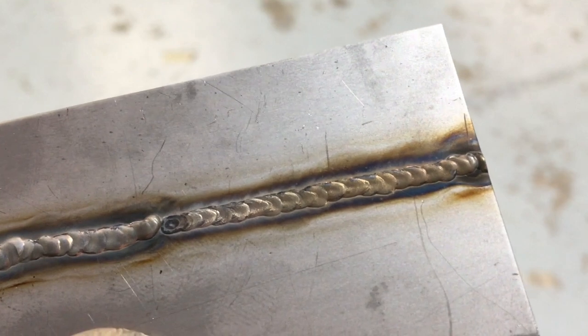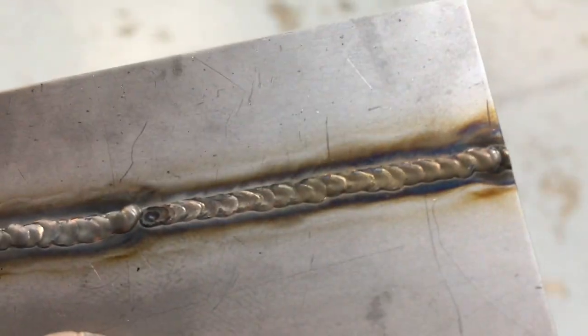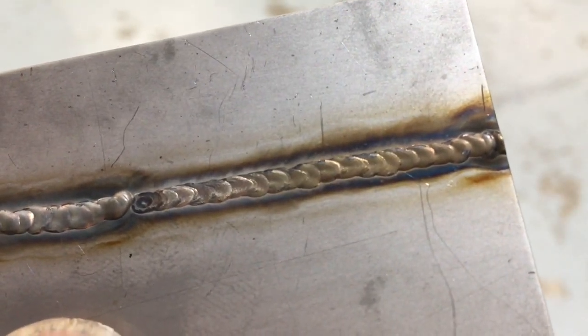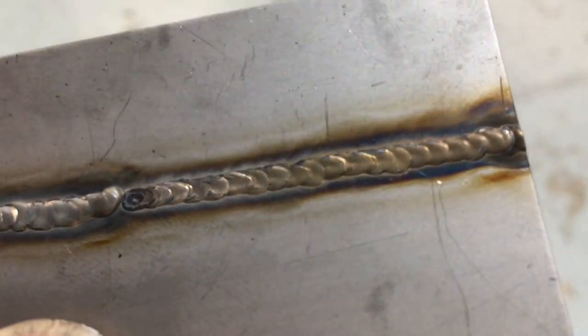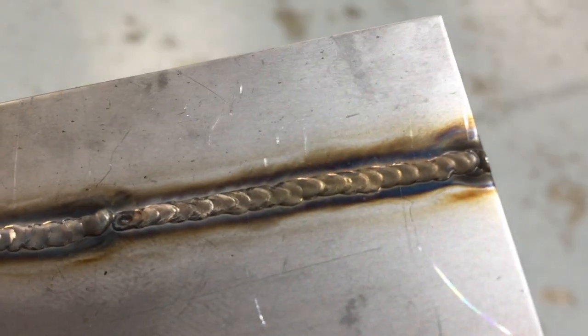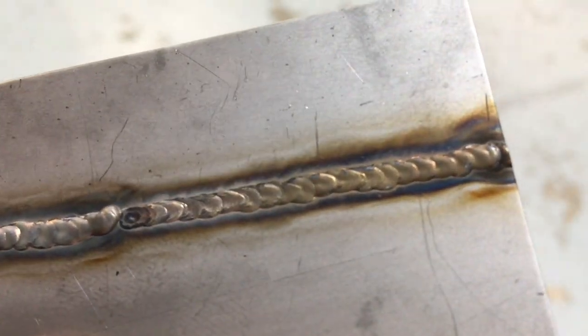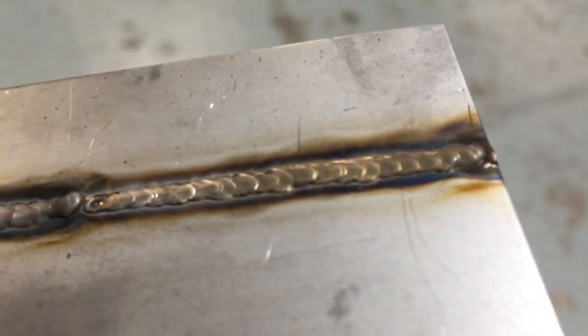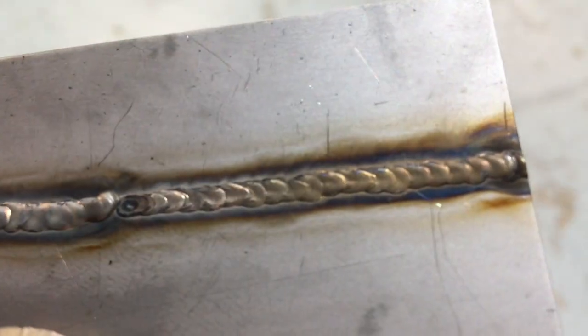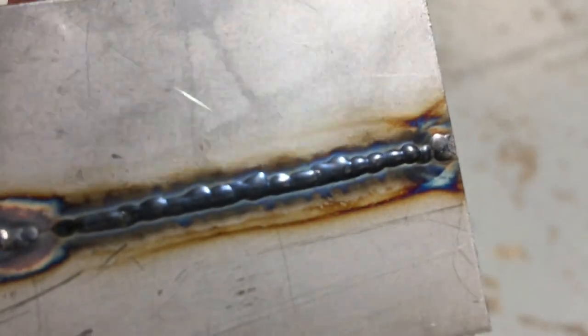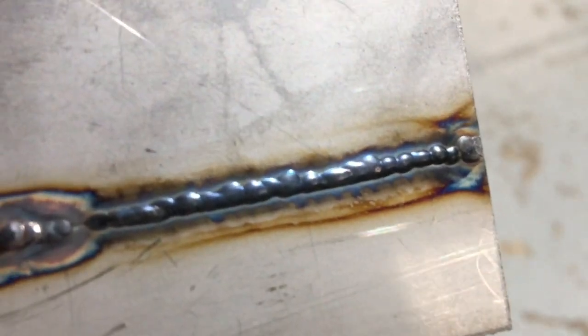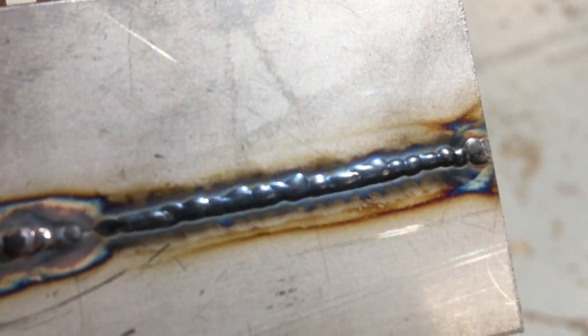Right, firstly, neither weld looks particularly good. Reasons for that we'll get into later, another thing to show you. But this is the first weld that was welded at a reasonable speed, and it does show a bit of promise. It's not crowned up, it's reasonably shiny, and the penetration is through the other side. There's been a lack of gas coverage on the back, which we'll talk about in a minute.